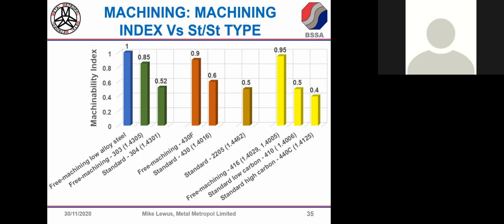And very quickly, there's two slides that just point to grades that have been designed to give you better productivity in a machine shop. The caveat is that all free machining grades rely on an increase in inclusions, so elevated sulfur. That immediately means in a marine environment, it's not going to perform so well, and it isn't something that I'd recommend being exposed even to a marine atmosphere. I mention it because I know people have been sold free machining grades because they wanted to produce more components that ultimately were going to be exposed in a marine environment. So I'm touching on this as much to alert you to the fact that free machining grades have lower corrosion resistance compared to their standard counterpart.